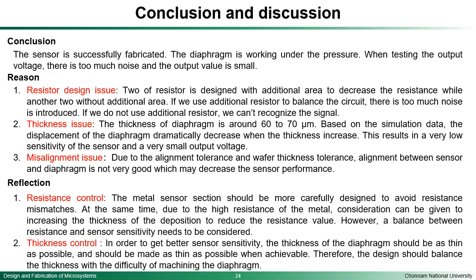For the second part, the output voltage is very low. That may be caused by two reasons. The first one is the thickness issue. Our diaphragm thickness is around 60 to 70 micron. Based on the simulation data, the displacement of the diaphragm dramatically decreases when the thickness increases. This will also result in a very low sensitivity of the sensor and a very small output voltage. Compared with the other groups, our diaphragm is 20 to 30 micron thicker. That's why our sample's performance is lower than the other groups.